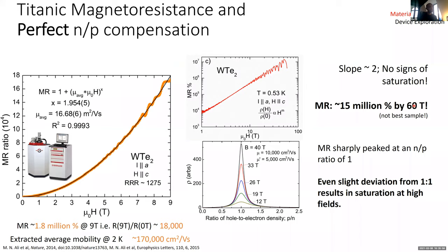The resistivities or the resistances? You mean the resistivity, right? Resistivities, yes, that's right. No, it's not in the mega ohms. No. So this thing is very metallic. Without magnetic field and at low temperature, it's down to maybe a couple hundred nano ohm centimeters. Increasing by seven orders of magnitude is still not even an ohm centimeter, you know? I see. Okay, good.